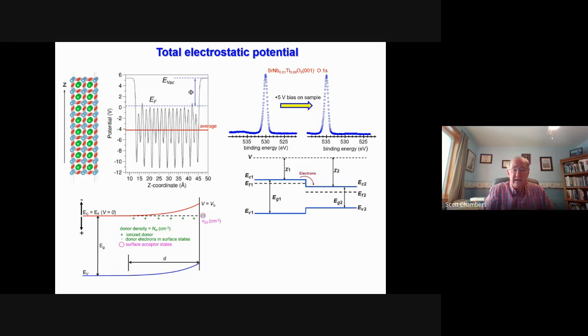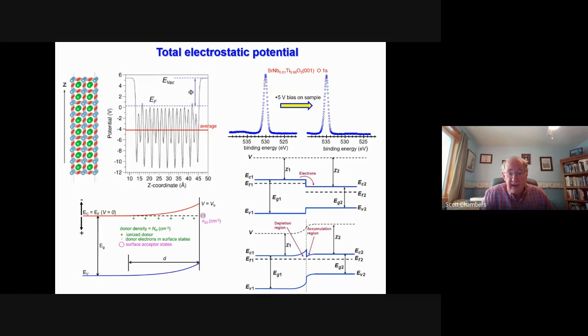And then if you bring two semiconductors together to make a heterojunction, then you can have discontinuous changes in the valence band maximum and the conduction band minimum. These are called band offsets. And this is obviously going to make for a big change in the potential within the material as you go from material 1 to material 2. And as you can see here, if we just think about bringing these two materials together, we have different Fermi level positions. And so the Fermi level is going to equilibrate, which means electrons will go from material 1 to material 2. By the time that happens, we're going to have something very complicated like that. So as you march through that material in the direction toward the surface, you can see that the potential is changing a lot. That's obviously going to have a big effect on core level binding energies and line shapes.